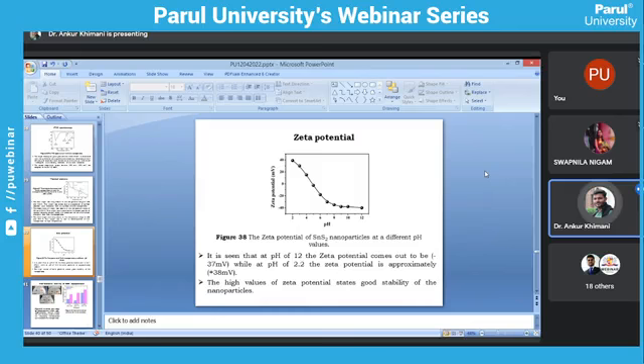Zeta potential. The stability of the nanoparticle is confirmed by the zeta potential. The zeta potential of SnS2 at different pH is observed. It is seen that at pH 12, the zeta potential comes out to be minus 37 millivolt, while at pH 2.2, the zeta potential is approximately plus 38 millivolt. The high value of the zeta potential states good stability of the nanoparticle. So for the stability, we have to do zeta potential.